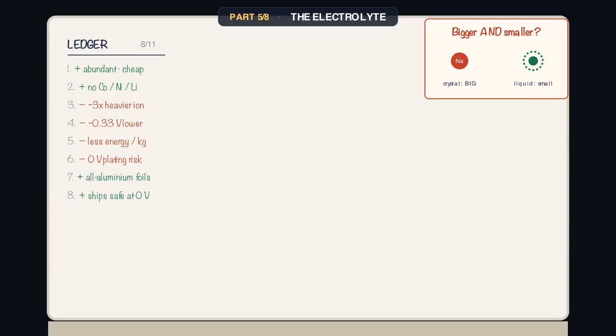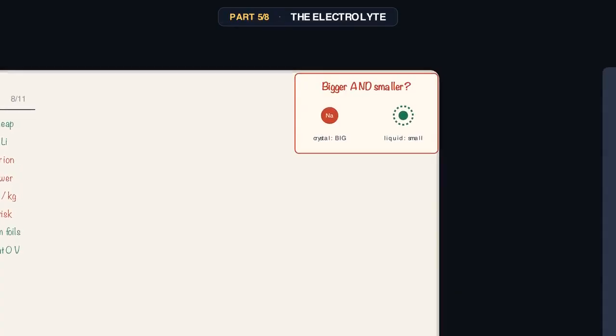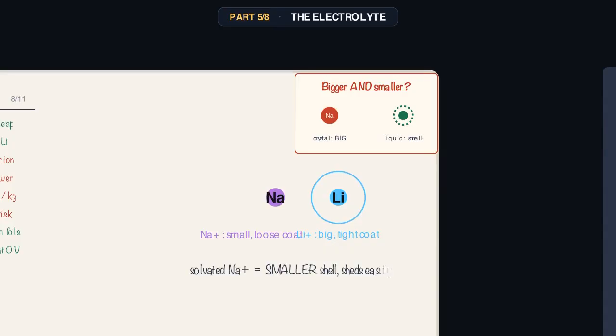And here, in this liquid, we finally meet the other half of our paradox. In the solid, sodium was the big, slow one, we saw that. But out in the electrolyte, sodium wraps itself in fewer, more loosely held solvent molecules than lithium does. Its solvated bundle is actually smaller, and it sheds that coat more easily. Bigger bare ion, smaller dressed ion. Hold that thought, because the payoff only lands when we take this cell out into the freezing cold. Not yet. One piece left.